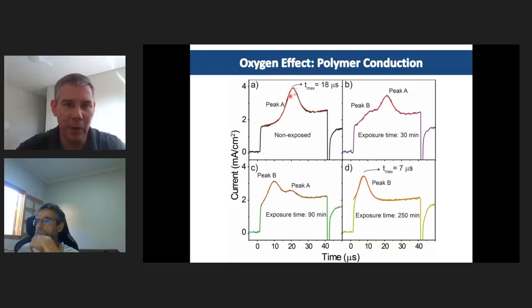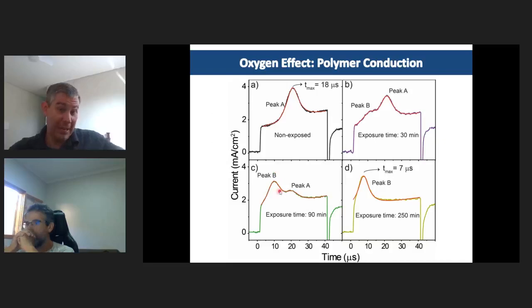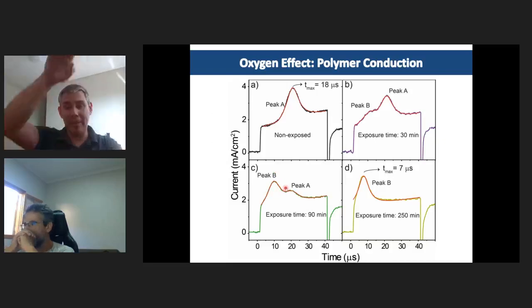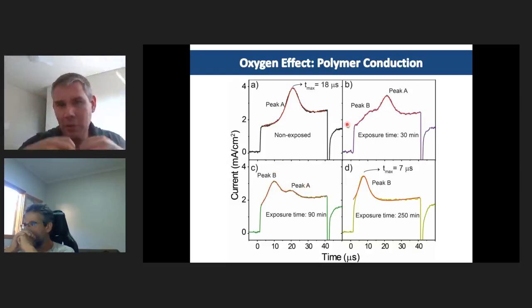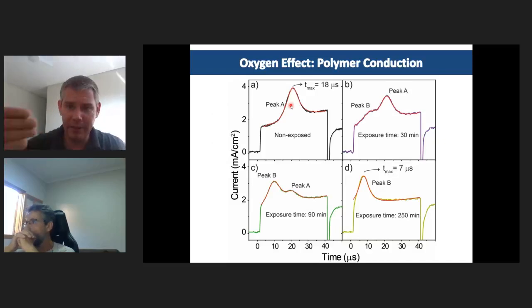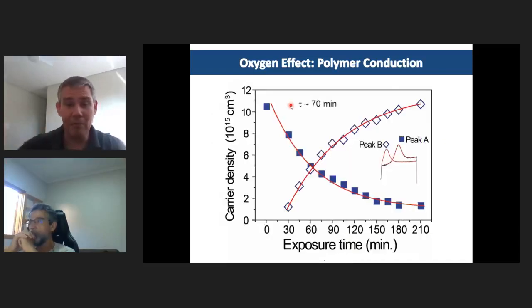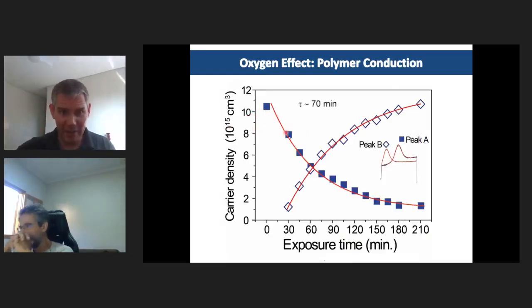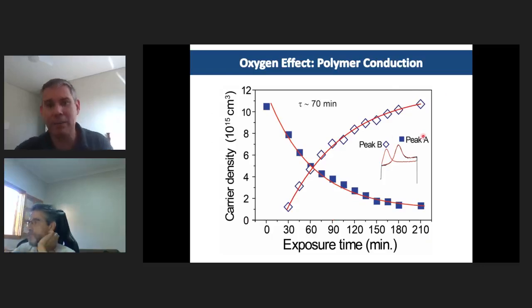summarizing the results. So no exposure, only peak A, and as I expose as a function of time, peak A sort of diminishes, and peak B, which is in the beginning of the extraction, starts appearing. And we can do a lot of things. We can integrate this curve here to calculate the amount of charge, and we did this over time, and therefore we can sort of recreate the disappearance kinetics of peak A and the appearance kinetics of peak B,